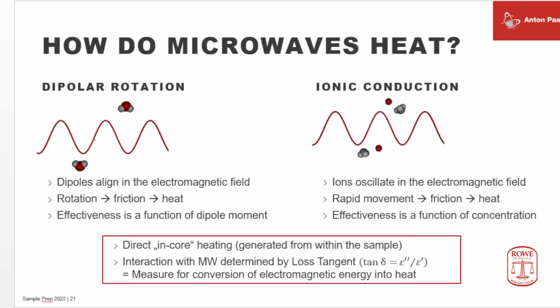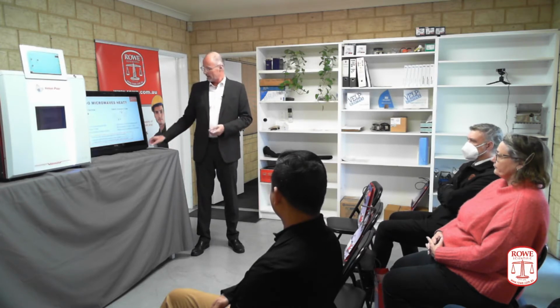The other mechanism is ionic conduction. Free ions in the solution would move in the frequency of the electromagnetic field, and also this free movement, molecular movement, is heat. The ionic conduction is dependent on the concentration of free ions in the solution. And this is, by the way, the explanation why distilled water would not heat very well in the microwave, whereas if you put just a small portion of, let's say, nitric acid into it to add some free ions to the solution, this heating mechanism works very well.